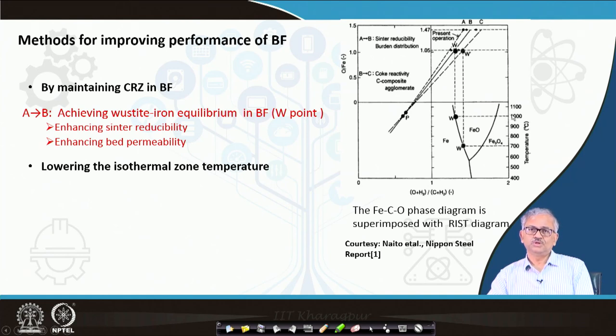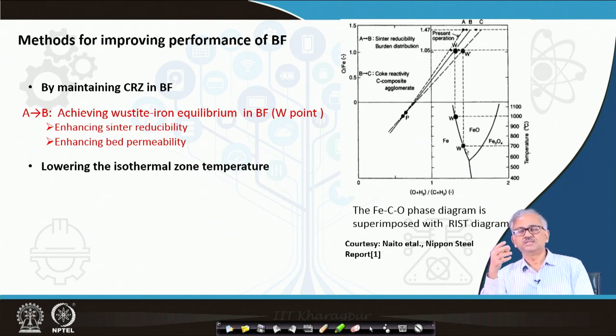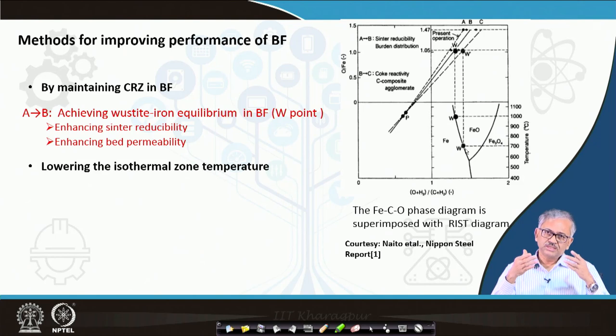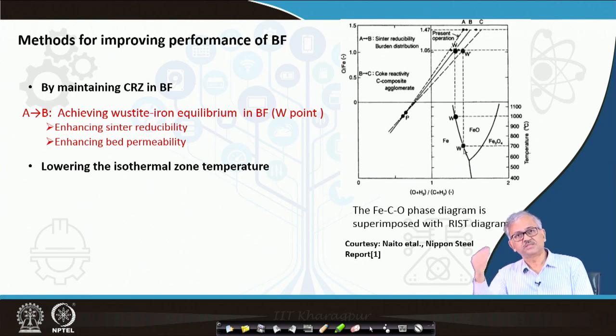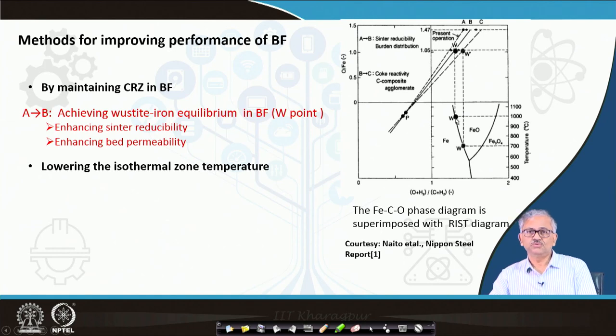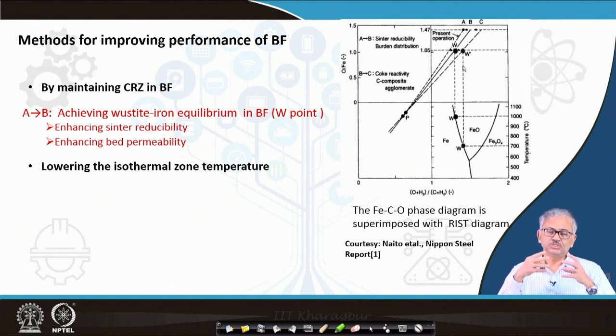If we can reduce the isothermal zone temperature — say to 700°C — we come further along the wüstite–Fe line, and O/C basically increases. That means CO utilization increases: at equilibrium, less volume percent of CO is in equilibrium. At 1000°C it was 70% CO; at 700°C maybe only 60% CO will be at equilibrium. As temperature decreases, this line curves so that the equilibrium O/C ratio becomes higher.